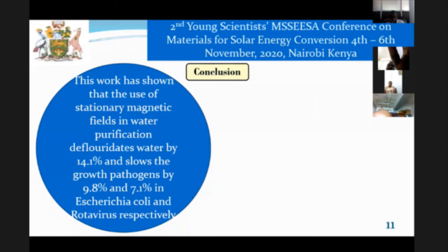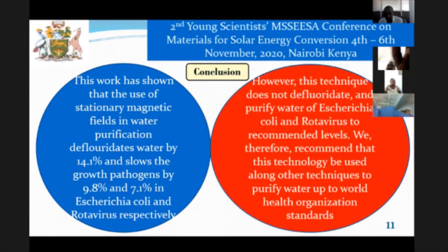So we can therefore conclude that this work has shown that the use of stationary magnetic field in water purification defluoridates water by 14.1%, and slows the growth of pathogens by 9.8% and 7.1% in Escherichia coli and rotavirus, respectively. However, this technique does not defluoridate and purify water of Escherichia coli and rotavirus to recommendable levels. We therefore recommend that this technology be used along other techniques to purify water up to the World Health Organization standards. Thank you.